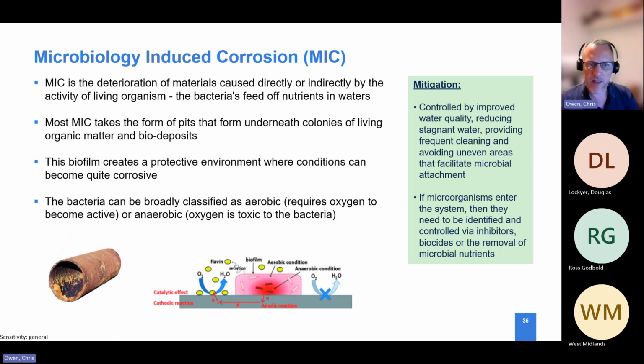As a result of that drain down process, water was being left behind. And again, where you've got dead legs or changes in geometry, places where water can collect, after a period of time that water can become stagnant and it can break down, particularly if there's bacteria in the water or the water is poor quality. These produce biofilms, and underneath these biofilms we can end up with pinhole corrosion, which can take place quite quickly. And again, going back to the case study on the thin wall tube, we started to see this happen quite a lot when they were first being installed.